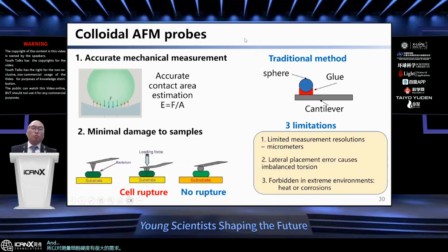And this is what traditional methods people implement for making spherical or colloidal AFM probes. Basically, they just attach, or glue, a microsphere on a cantilever. So this method has several limitations. First, it's limited to micrometer scale, so you cannot get a very high spatial resolution measurement. Second, they are done in the optical microscope. It's not aligned very precisely, so you will get imbalanced position. And because it's glued, it's not very good for liquid environments, also for some extreme environments, for example, heated environments or corrosive environments. But the spherical probe has this kind of advantage because it's easy to predict the contact area.